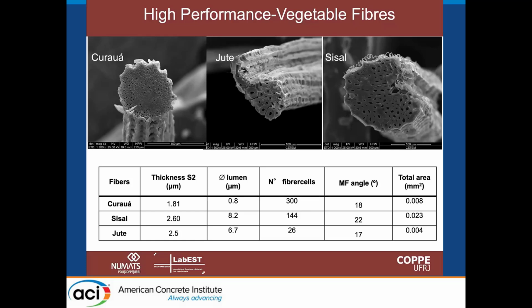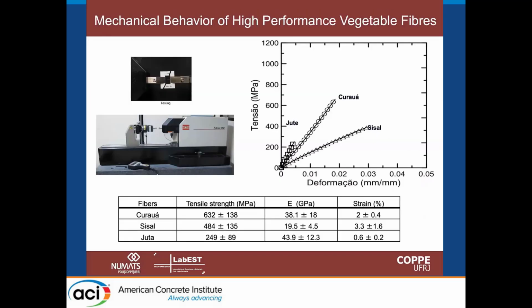These are very high performance fibers. They can resist up to 500 MPa. They have elastic modulus that can range between 20 and 40 GPa. This is somehow in the same range of many synthetic fibers or even higher. So the jute fiber, for example, can have the elastic modulus that is similar to PVA fibers, and the other natural fibers have higher properties than polypropylene, nylon, and other synthetic fibers.